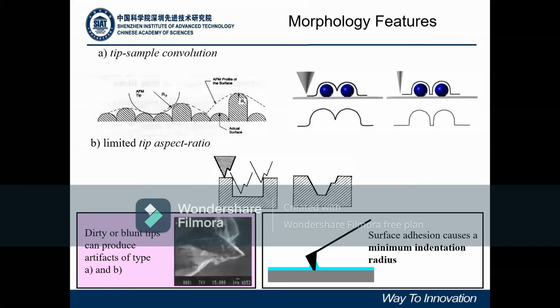The scan is also limited by the radius of the tip while scanning. For example, when the probe is broken or something is attached to it, these features are then present inside the morphology, and this can produce artifacts as well. Scanning in air, there is always water capillarity adhesion that increases the force between the probe and the sample, so there is a minimum indentation radius that can have some morphological effect.